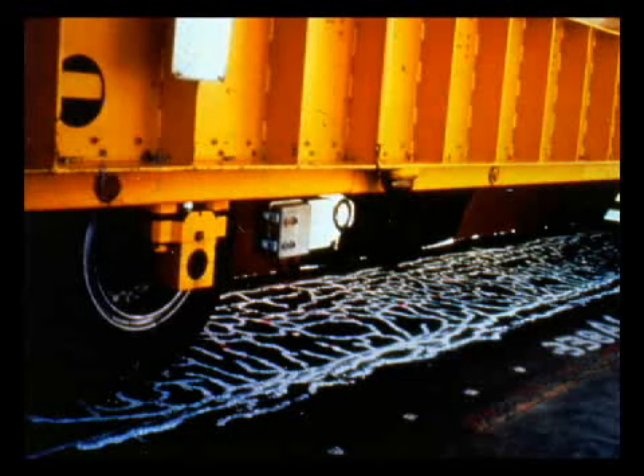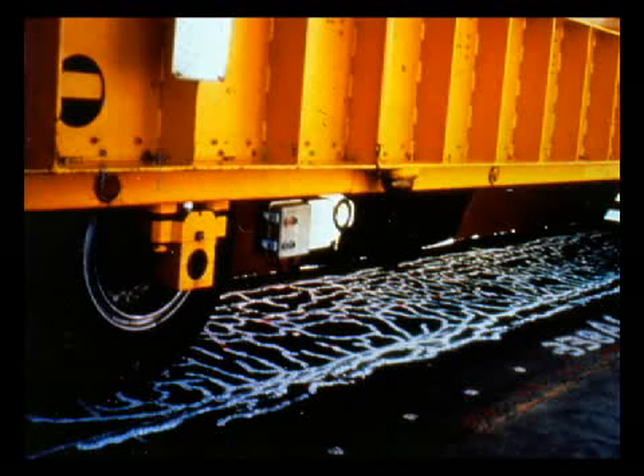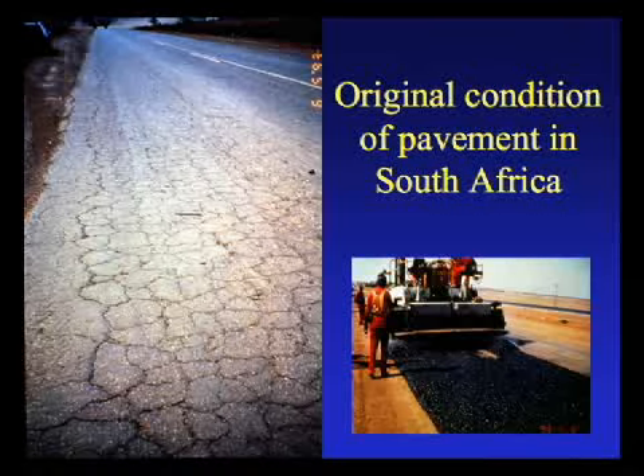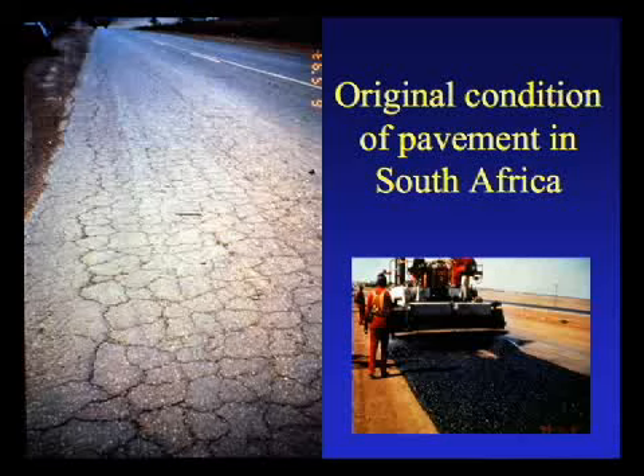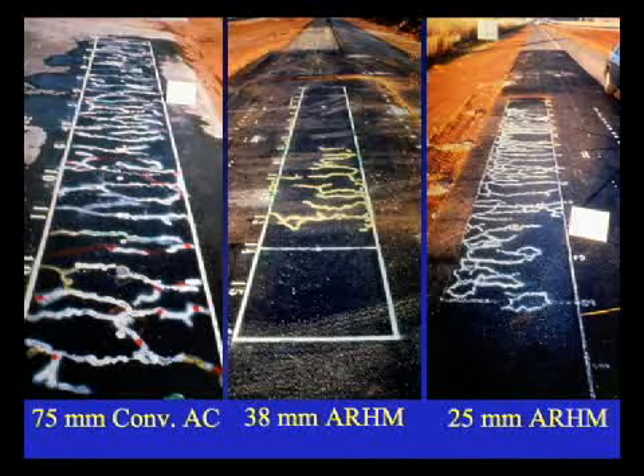And what all those white marks are is as the pavement cracked, they would go out and spray it with paint so you could see where the cracking was. This was the original pavement that we looked at. We tried to find something like Ravendale. You can see the extensive cracking. We designed the mix in California and placed it in South Africa. These are the results of the overlays and the testing.